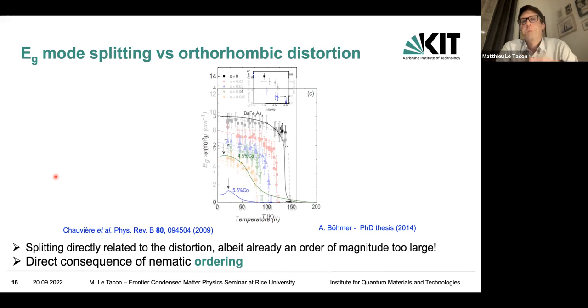So if we have a splitting which is 10 wave numbers in the iron-based compound, maybe in the nickel-based one we should be able to see a splitting of the order of 1 wave number, something like that. It's a very small effect, but it should be possible to resolve it. And even if it's smaller, we should at least see a broadening of the line.